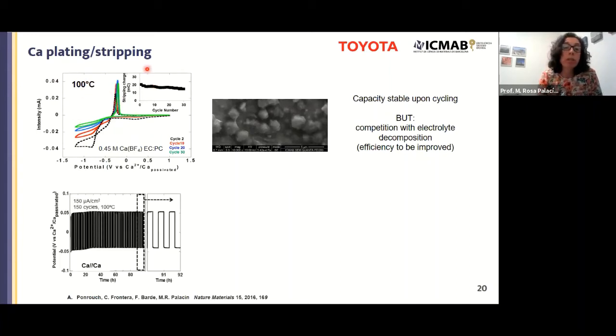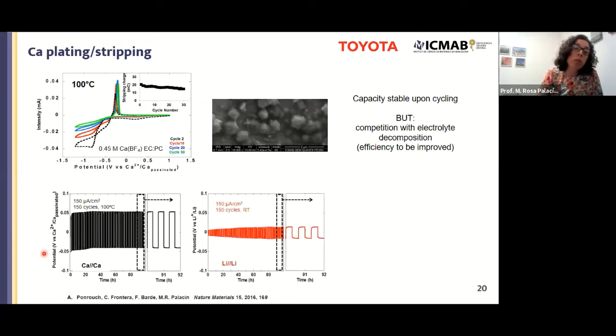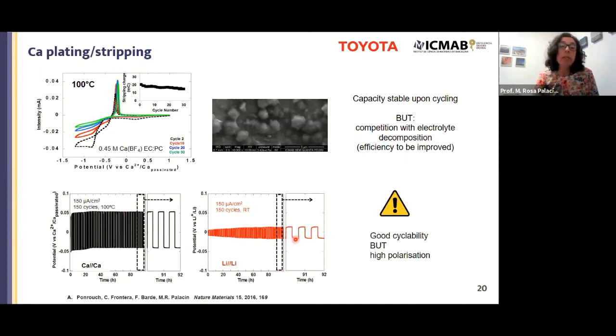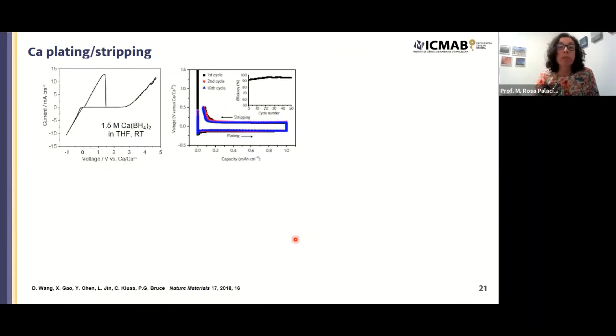Here there is a benchmarking on lithium and calcium anodes. Here you can see calcium-calcium symmetric cells at 100 degrees C. You can see that they work fine. The only issue is that the polarization between oxidation and reduction is very high. And here you have lithium-lithium symmetric cells to compare at room temperature, and you see that this is much lower. But still, it is really a starting point.